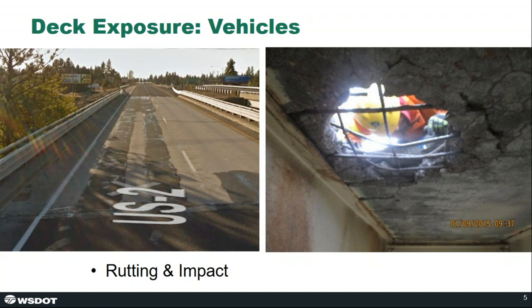On the right, you see a full depth failure of a bridge deck in service. Rutting and impact are related because as a bridge deck ruts, it becomes rougher and that increases the dynamic pounding that truck axles deliver to the bridge deck, which leads to spalling, delamination, and larger failures as you see here. One of the big keys to avoid rutting is the use of hard aggregate in our concrete.